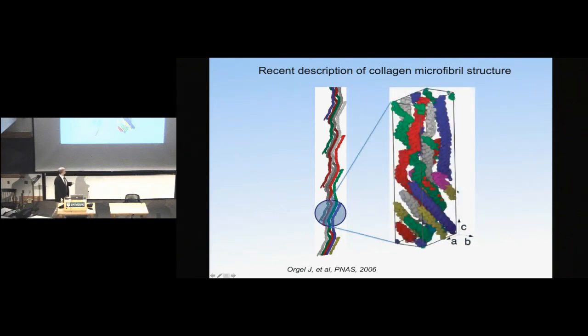And we have this structure, which was only recently identified, in which there's a somewhat twisted conformation of these collagen molecules. It's actually a very mild twist. This is shrunk down by a factor of 30, so it looks much greater than it is. These are almost straight rods, but not quite. So then the question is, where does the mineral go in there?